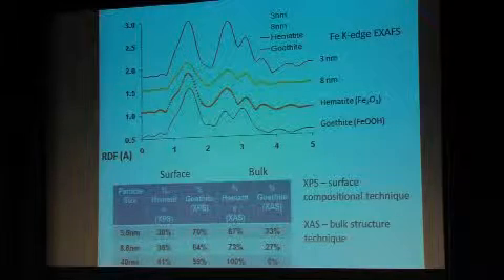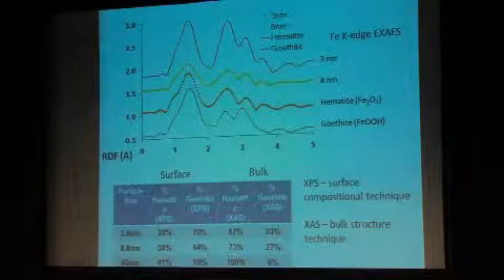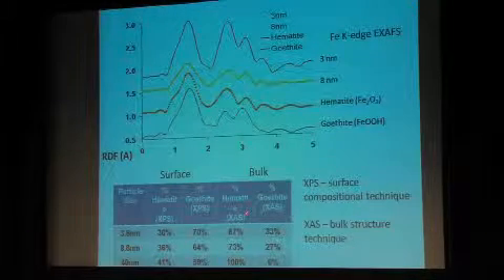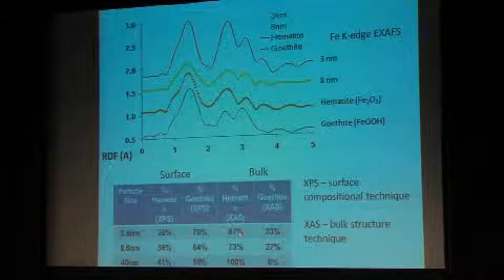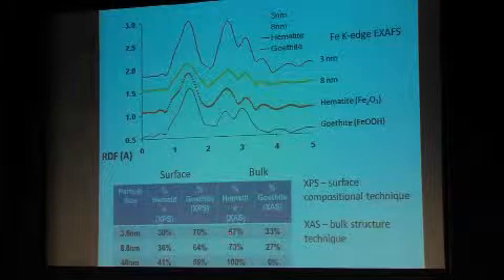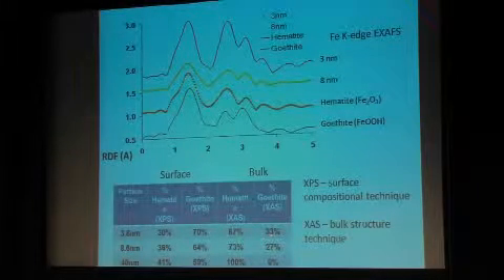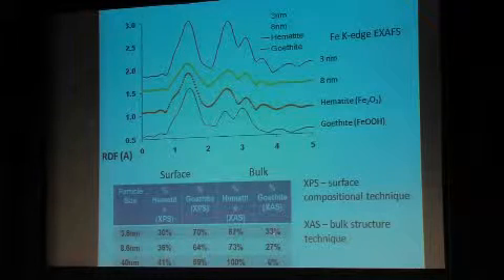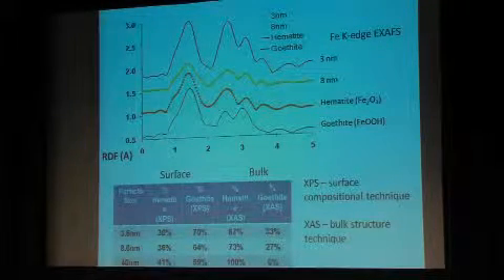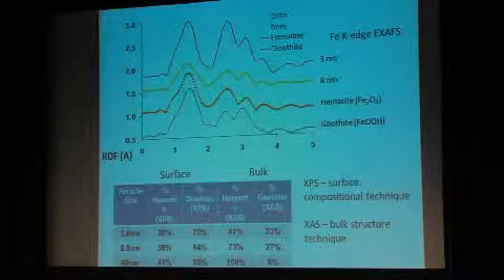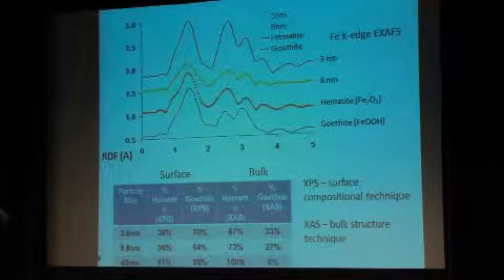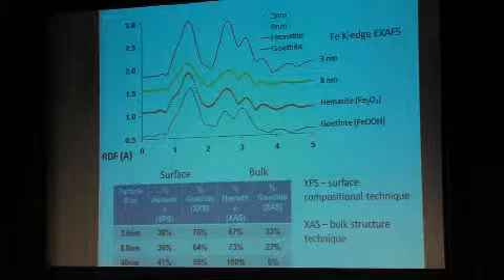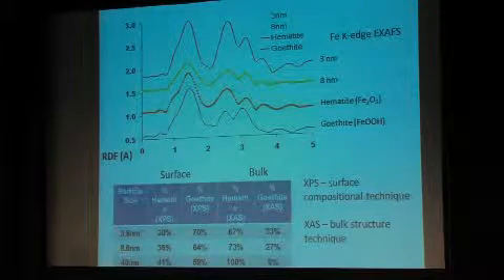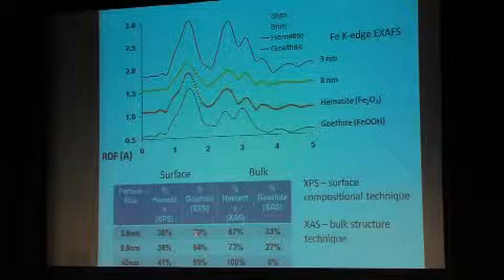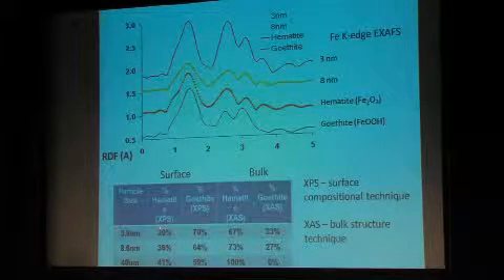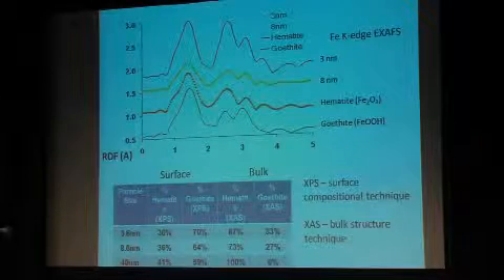So based on the bulk method, which is the XAFS method, which is measuring everything, when you get to the smallest particles, X-ray diffraction says it's hematite, but XAFS says that a third of the structure is hydroxide, not oxide. And then when you get to the larger particles, they're all oxide. Now, there may be some hydroxide at the surface, but it's such a small proportion you're not picking it up. With the XPS, you do see that. You see that at the surface itself, that you've got this hydroxide surface, and then as you get to smaller and smaller particles, it's got a more hydroxide character.